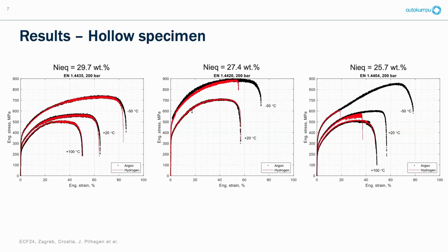And perhaps for the 4404, which is the most interesting for the research community, a lot of things happen. At elevated temperatures, you have no observed embrittlement, but it embrittles at room temperature, and even more at -50. You can also see a lot of deviation in the load at room temperature, but you don't see it at, for example, -50. So that perhaps indicates different cracking behavior, like crack propagation and arrest.